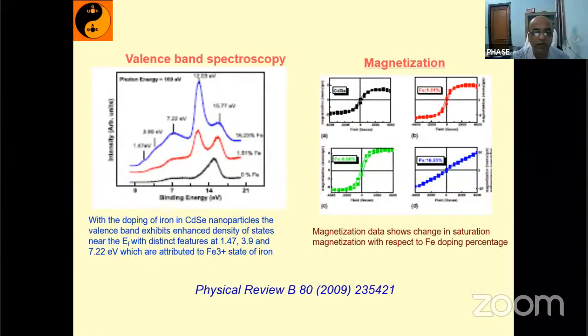But here you can see that you have got the information about the iron from this valence band spectroscopy using synchrotron radiation, which is basically correlated with the magnetization measurement. And one publication has come from this synchrotron radiation work. So this way, very good quality or high quality research one can do using this synchrotron-based photoemission spectroscopy.